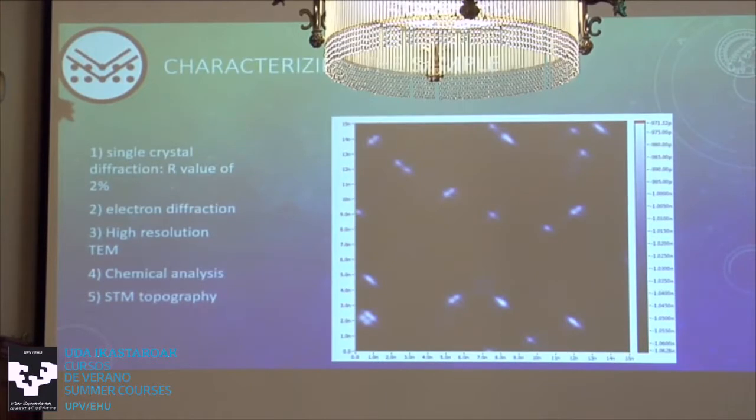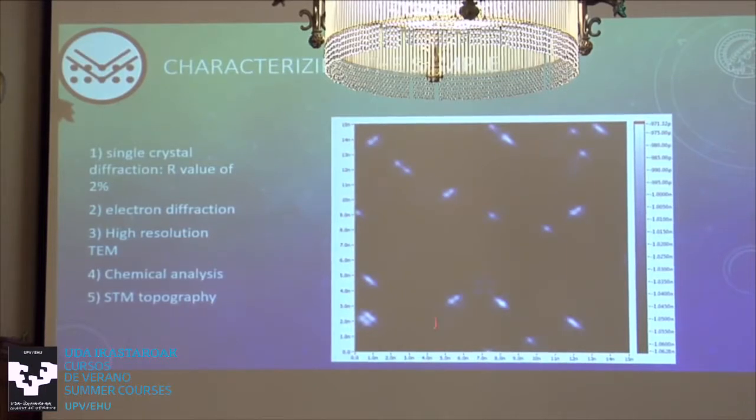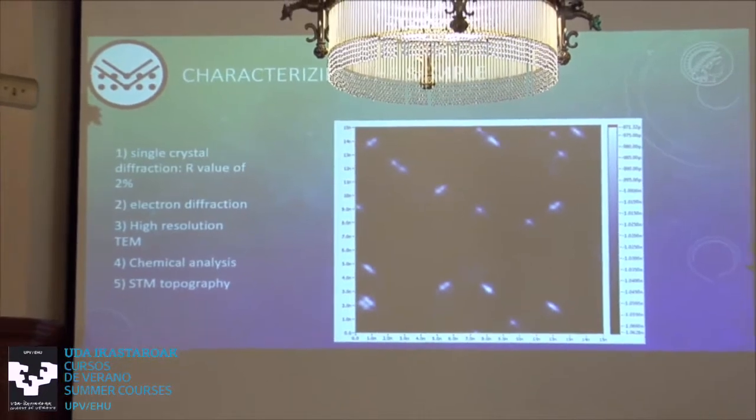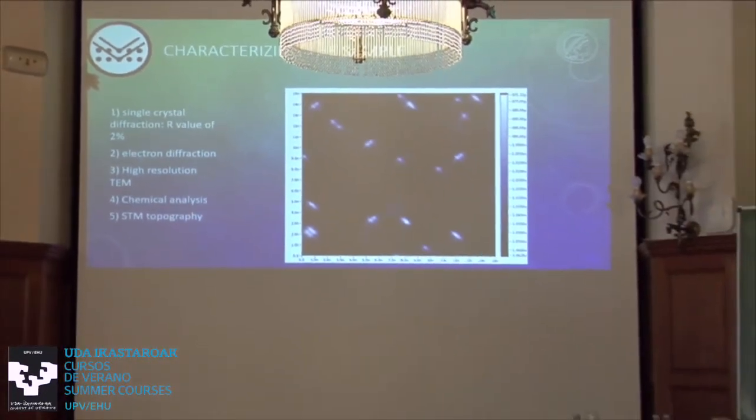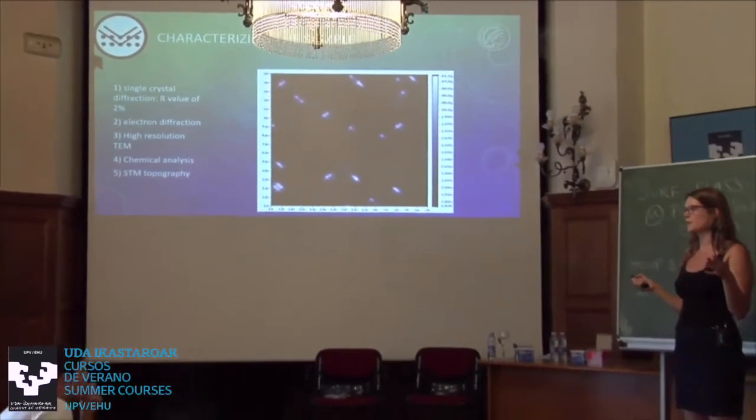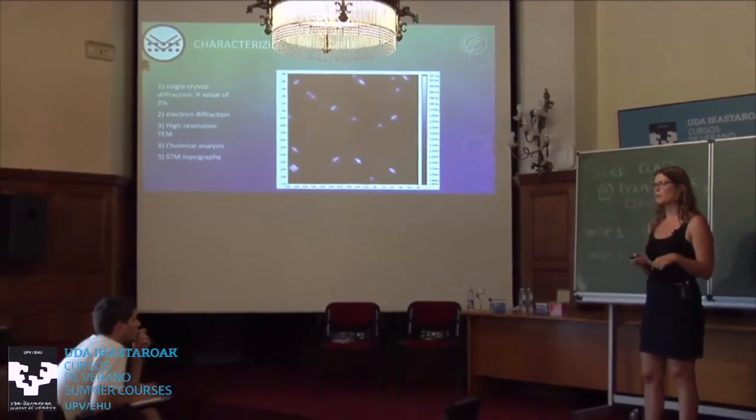And then lastly, we did some STM topography to get an idea about how many defects we have. So these bright spots are defects. And this scan is on the very first samples I grew before I improved the methods, and we already only had about one defect every 50 unit cells, and we could improve that. So this is actually a compound you can grow relatively defect-free.